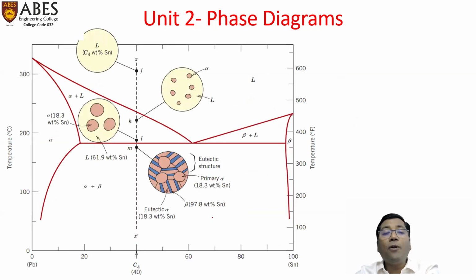Similarly, we consider this point C4. The composition C4 means 40 weight percent tin and 60 weight percent lead. Starting from point J, here it is completely liquid. Inside this, alpha plus liquid. So alpha starts to precipitate, solidify, and liquid is also there. So in the liquid, a few chunks of alpha would be there. Then at point L, a major portion gets converted to solid and liquid is very little. And at this point, this alpha would still be there, and this lamella of the eutectic combination will form. So this eutectic structure would also be there.